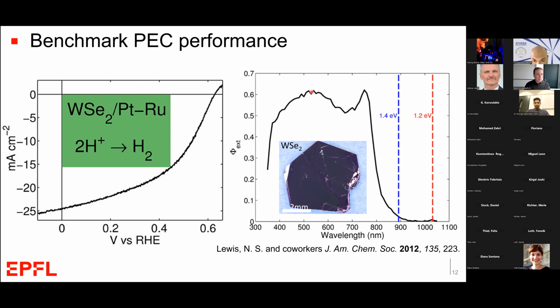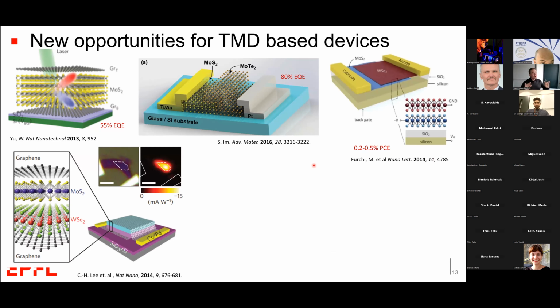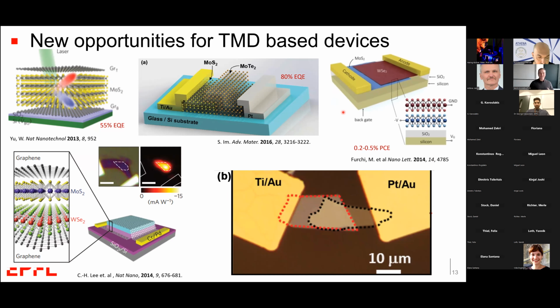So that's when our group became inspired by the layered crystal structure of these types of materials, which allows the exfoliation into two-dimensional or few-layered type nanoflakes or sheets, which have been shown by many groups to have exceptional optoelectronic properties in many different types of optical sensors, even photovoltaic devices here. But if you know about this field, typically these flakes are produced by the Scotch tape method or mechanical exfoliation, leading to essentially devices on the size of a micron or a few microns squared. So again, using this for a large area solar energy conversion maybe isn't so viable. Our lab wanted to find a way to coat over large areas these types of nanoflakes or nanosheets, so we could eventually demonstrate large area hydrogen production using these types of materials.